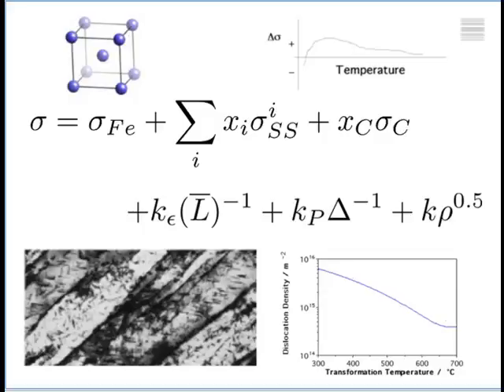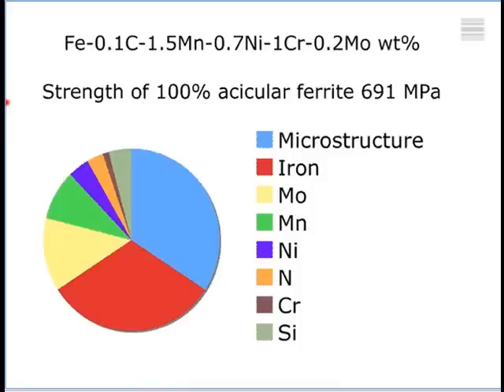So the topics that I've summarized here are for a single phase. And just to show you the contributions that they make in real life, in this pie chart here, there's a particular microstructure which is effectively bainite, which forms on inclusions. I have a total strength of 690 megapascals. Pure iron itself contributes about 220 megapascals. The microstructure, that means the size of the crystals, contributes about another 250 megapascals. And then we have solid solution strengthening contributions from the other alloying elements which are in the steel. And this is the composition of our steel.